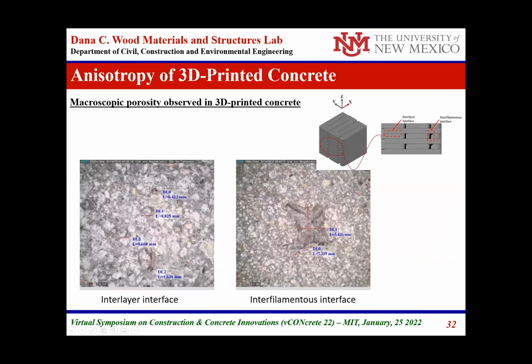To examine this, we took sections and looked at the voids at the interlayer interface and the interfilamentous interface. We noticed that the interfilamentous interface could have higher void dimensions. They are not continuous, but there are voids larger in dimension than the micrometer-scale ones typically seen in the interlayer interface.